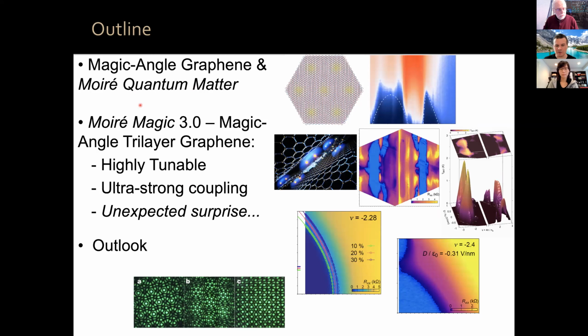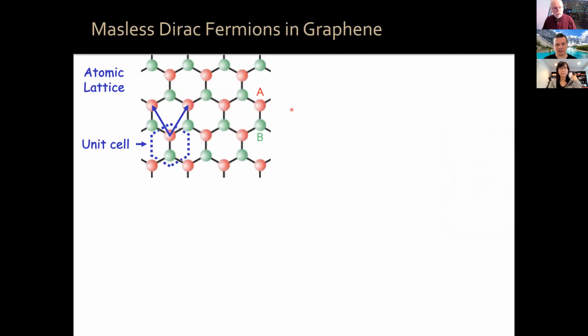And then I will introduce you to the next generation Moiré quantum matter system, which I call Moiré Magic 3.0. It's magic angle twisted trilayer graphene. It's a much more highly tunable system than the bilayer case. It realizes ultra-strong coupling superconductivity, and I will show at the end an unexpected surprise related to in-plane magnetic field measurements. This system is likely a spin triplet superconductor. And then I will tell you just a little bit about some of the outlooks, what else is going on in nearby fields. So let me remind you, everyone, what graphene is.